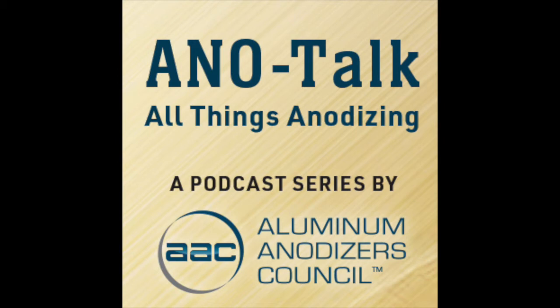So referencing Mark's original point around sulfuric acid, what does type 2 represent? Type 2 represents conventional anodizing, which is typically done at 68 degrees, at a current density of 8 amps per square foot and as high as 15 or 16 amps per square foot. But it's designed for cosmetic applications, not necessarily for high abrasion resistance. That's what hard coat's designed to do.